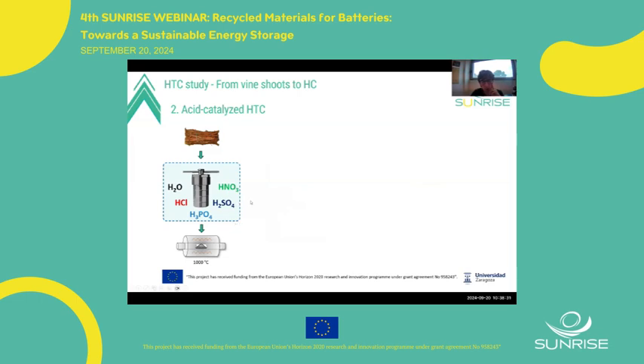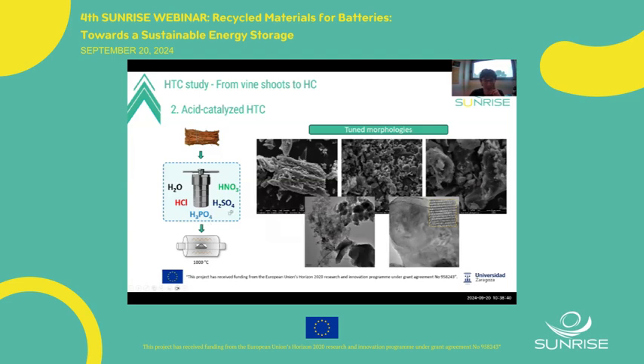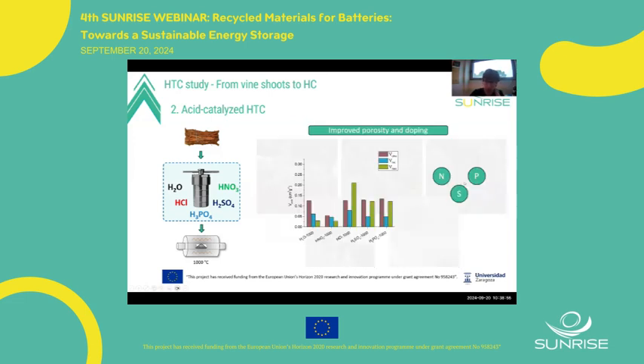Mainly the hydrolysis of the biomass, and also to dope the material with sulfur, nitrogen, and phosphorus. With this different hydrothermal carbonization, we obtained different morphologies in the hard carbons, for example more nanospheres or more 2D regions, more ordered ones or less ordered ones, as well as inclusion of heteroatoms and the development of mesoporosity mainly.